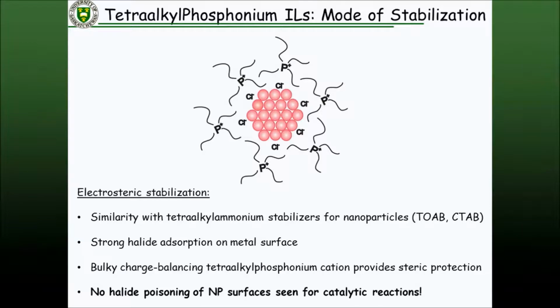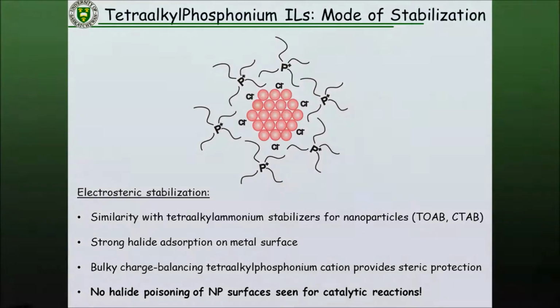And this is so-called electrosteric stabilization. You have an electrostatic stabilizer, if you will, in terms of a negatively charged chloride, but then you've got the steric bulk of the cation that is also there. If you think about this, it is very similar to a lot of things you see in nanoparticle literature for the tetraalkyl ammonium groups. So tetraalkyl ammonium bromide, cetyl-trimethyl ammonium bromide, very common surfactants for stabilizing nanoparticles. Here's a phosphonium system that's effectively acting as a surfactant and a solvent for nanoparticle stabilization.